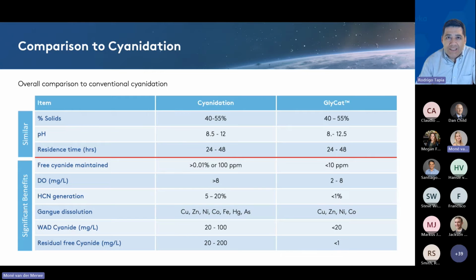Finally, when we look at the WAD cyanide, Glycat shows levels below 20 milligrams per liter. This is a substantial reduction from the typical range of 20 to 100 milligrams per liter found in conventional cyanidation, indicating that Glycat is a more efficient, safer, and less toxic technology.